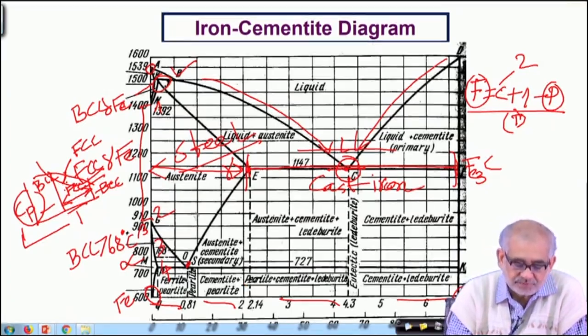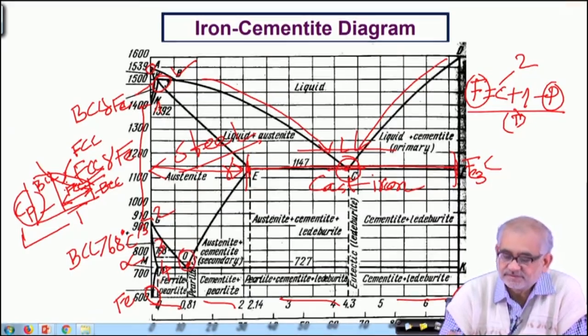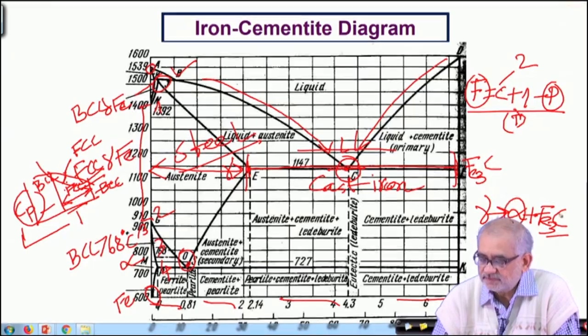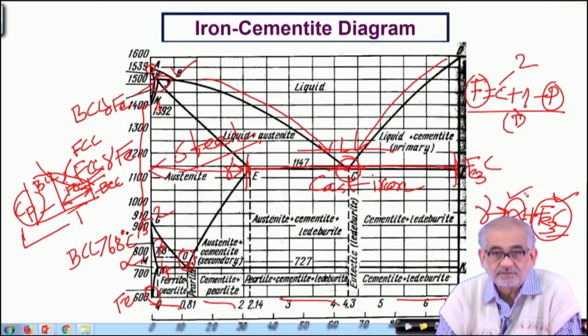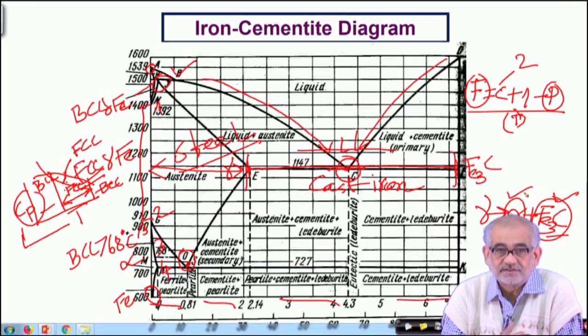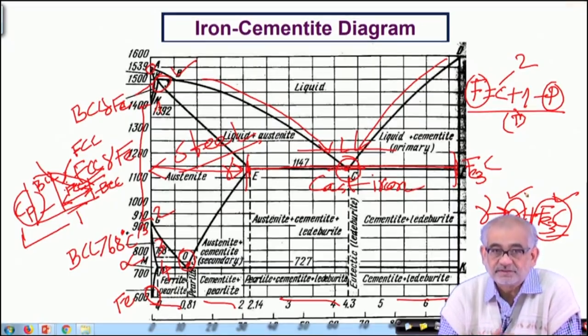The most important transformation for steel is the eutectoid change, where gamma simultaneously transforms to ferrite and cementite. Ferrite is a solid solution and cementite is an interstitial compound. The combination of this very hard phase with a relatively softer matrix gives you a product whose mechanical properties can be varied over a wide range — mechanical strength anywhere from a few hundred to over 1000 MPa, and ductility as low as a few percent to close to 100 percent, depending on the microstructural state.